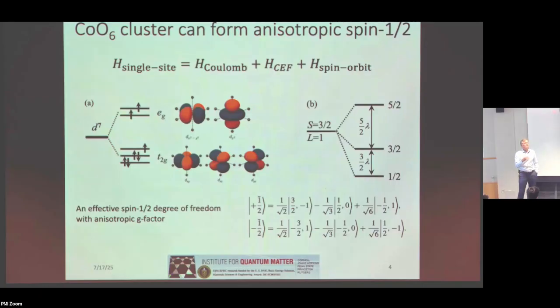And you might initially say, well, how am I going to find an Ising spin? Because the spin is detached from real space entirely. It just lives in its own rotation in space. And the answer is basically spin-orbit coupling can couple the spin back into the real space. And you need to have the right conditions for that to actually come into play. Because if I have a low enough symmetry situation so that I end up with an orbital singlet state, and the filling is correct, then I may end up with a very isotropic spin degree of freedom. However, in the case of cobalt, with 6-fold coordination, CoO6, since there are 7 d electrons that can populate these now split, this is now split 5-fold.